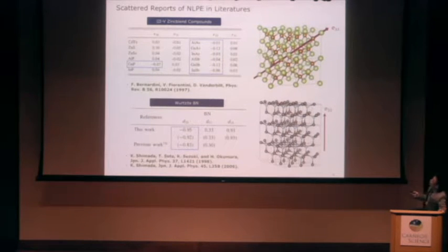They looked at the piezoelectric coefficients for some III-V zinc blende semiconductors. As you can see, quite a few of them have, even though small, negative e33, in this case along the 111 direction. It turns out wurtzite boron nitride has a pretty decent negative d33, reported in these two papers. So now the question is, what is the origin of this negative e33, and can we design piezoelectrics computationally?